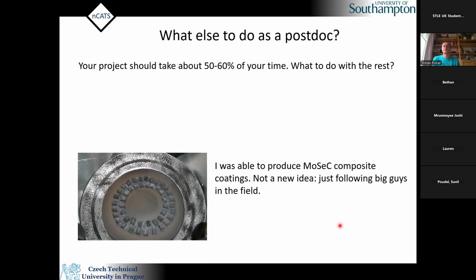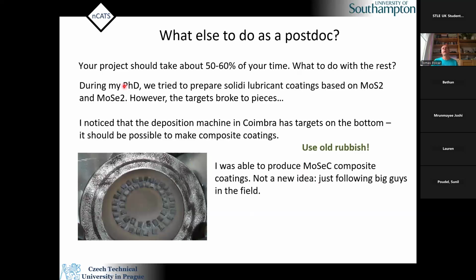During my PhD, I wanted to produce molybdenum diselenide coating as a solid lubricant, but the target broke to pieces. So I ended up basically with some small fractions of target, completely useless. But when I was in Coimbra, I noticed that they have a target which was placed not above, sputtering down, but on the bottom, sputtering up. So my idea was, okay, I can use these pieces, which I brought from my PhD time. You can see these small squares, more or less here. And I can place them on the target, for example, carbon, and then I can sputter composite material.